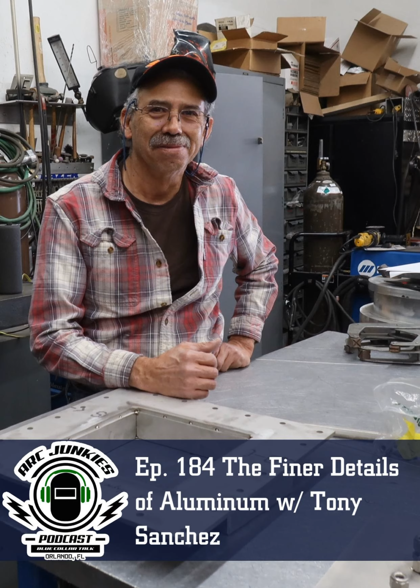Now, I mean, that does happen. You can pull slag up to the surface, but the majority of the time, you still have slag underneath that weld if you didn't clean it out. And then it's even worse than a cyclically loaded structure, because now that weld wants to start opening up, because now you've got that pocket in there. So you put things under pressure or cyclically loaded, and it's going to start propagating. It's going to start spreading and cracking.